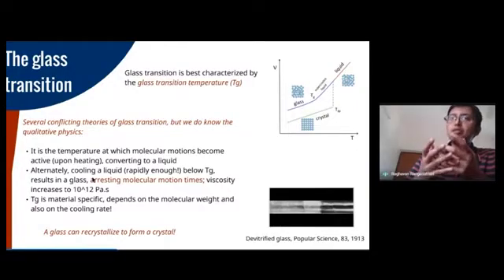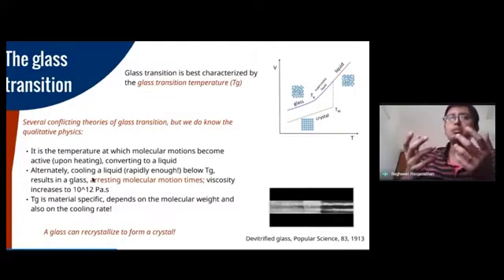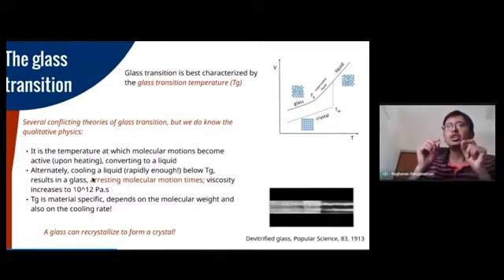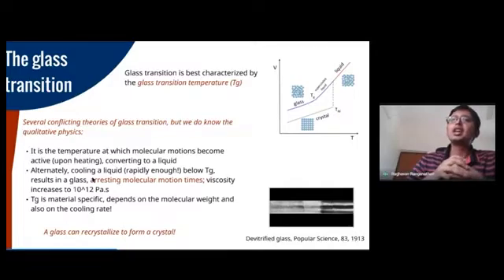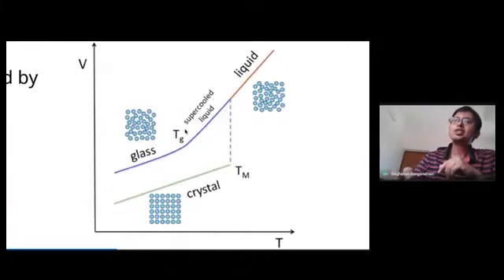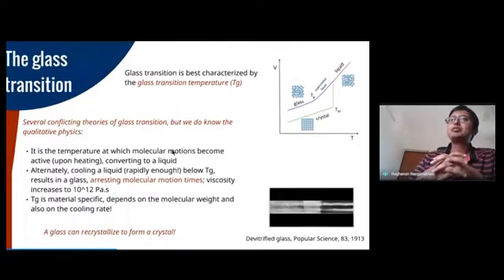Okay? And what's also very interesting is the glass transition temperature is highly material specific. It depends on what are the atomic species that are present in the material, what's the molecular weight of the material. For instance, if we talk about polymers, then a polymer that's very short versus a polymer that's very long have drastically different glass transition temperatures. And what's more interesting is this temperature Tg is not actually well defined. It is a function of how fast you cool the glass. So cooling the glass faster can give rise to glass transition temperature that's quite different from cooling it slower. So these are some physics that have perplexed scientists for long, but there are some understanding that's developed from several years of research in this field.